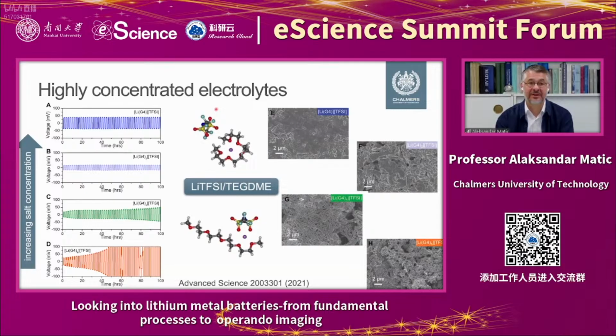One can look from the electrochemistry that when you have a low salt concentration, the overpotential in a symmetric lithium cell increases very rapidly, so you have formation of a very resistive interface. Increasing the salt concentration, the overpotential decreases and in the end becomes very stable. And if we compare to the right the SEM images of the surfaces of electrodes retrieved from cycled cells, you can see that at low concentrations it's a very inhomogeneous deposition, and at high concentrations it's very, very smooth.